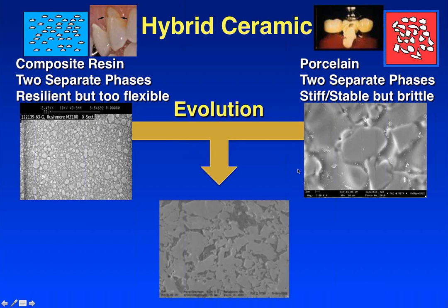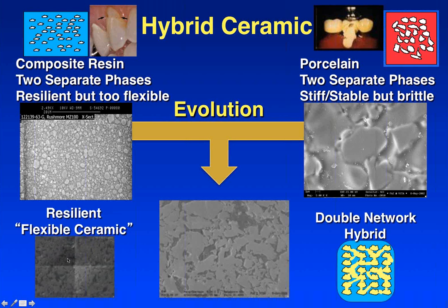So the idea was to try and combine the properties of both of these, and that was done by creating a ceramic network here that's all interconnected, and a polymer network that is also all connected, and they are connected to each other. So we create a material which is somewhat flexible. This happens to be an indentation. Usually when you indent ceramics, you tend to see cracks. You don't see that here with Enamic. And you have all of your ceramic particles in the yellow here that is connected, and all of the polymer in the blue connected, and all connected to each other.